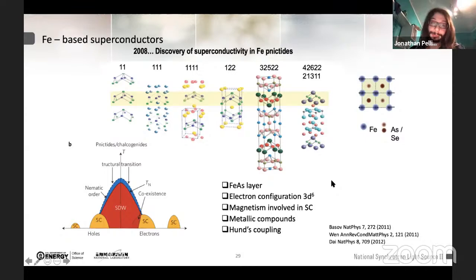However, in all of these materials, there is something that is common, which is an iron arsenide or iron selenide layer, which is where the interesting physics is, in particular where the superconductivity is and where the iron is present with a 3d6 electronic configuration. And most of these materials, in the parent compound, are antiferromagnetically ordered. And this is important because when we look at the generalized phase diagram of iron-based superconductors, we have a parent compound that is antiferromagnetically ordered. And then as we dope the system with either holes or electrons, we suppress the antiferromagnetism and we gradually induce superconductivity with a typical superconducting dome.